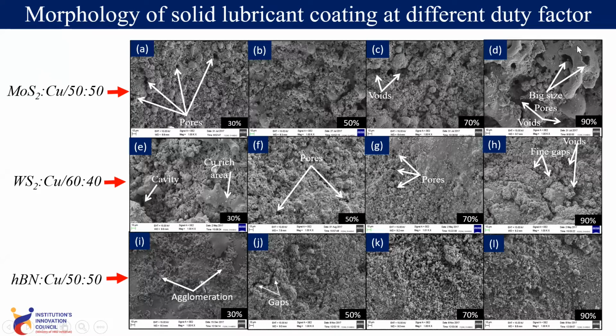So when we are increasing the pulse on time, a large amount of current goes through the electrode and more material gets eroded from the tool surface. But it accumulates in large amounts in the spark gap, so it will not flow with the dielectric. So arcing takes place. It means the same spark is generated at the same location, because there is a large amount of material in the spark gap.